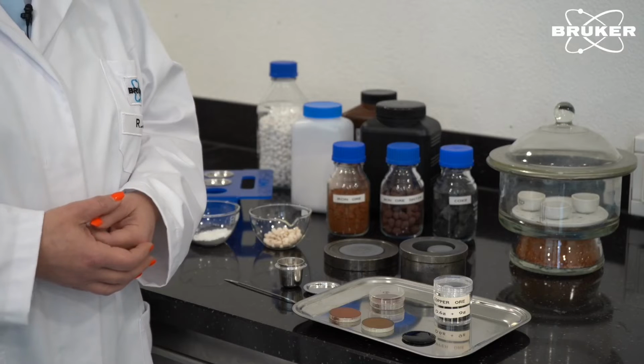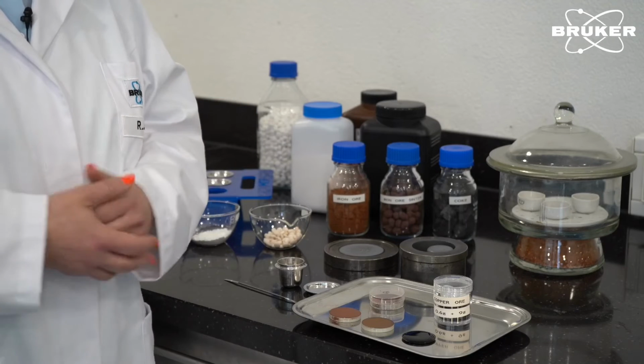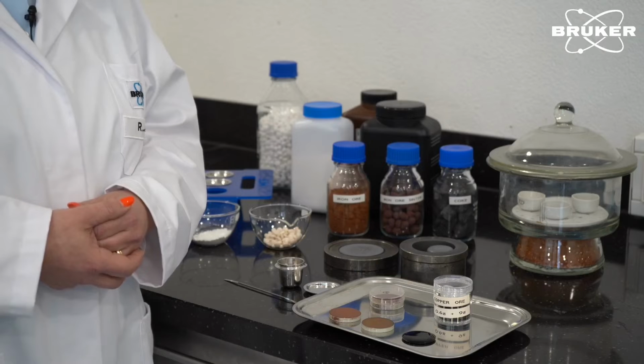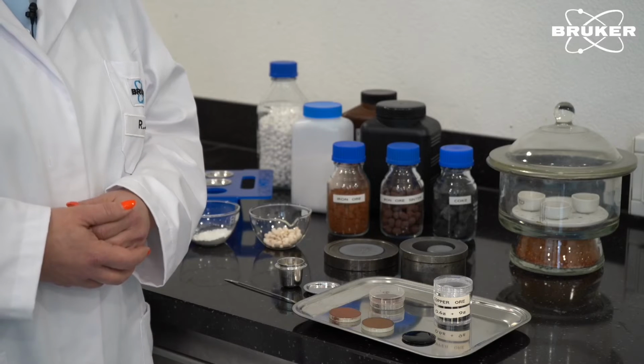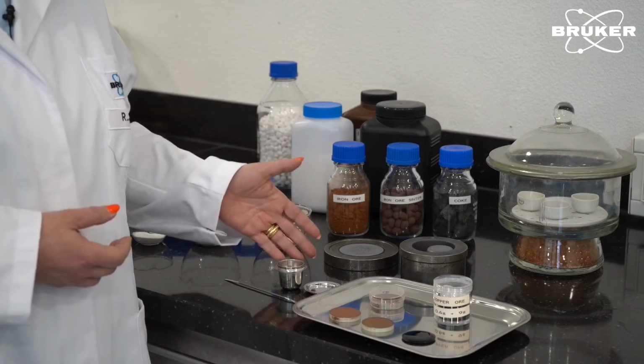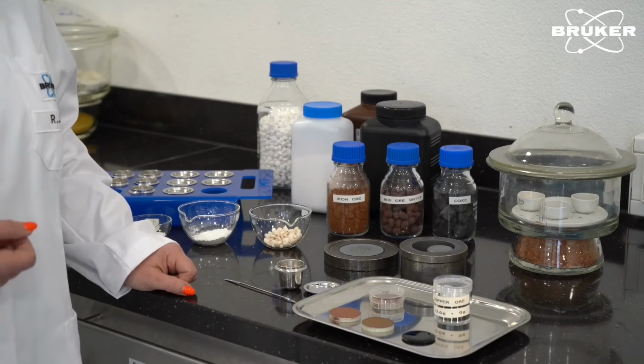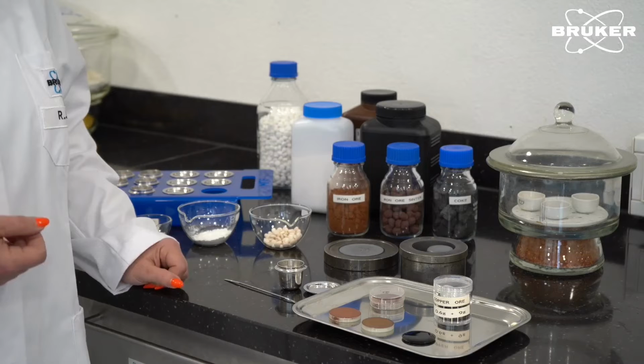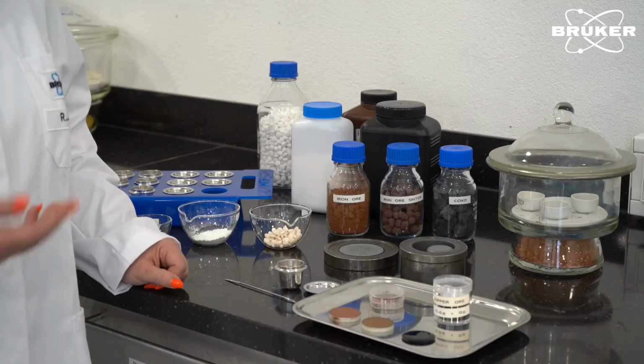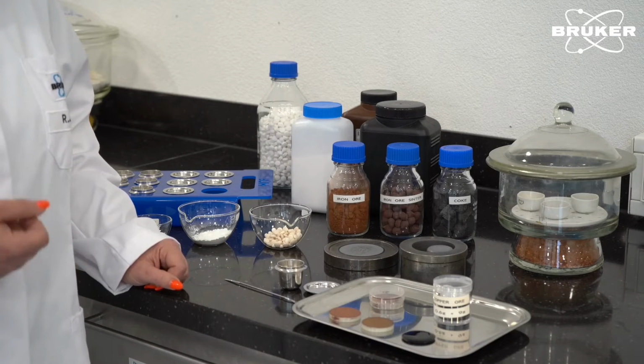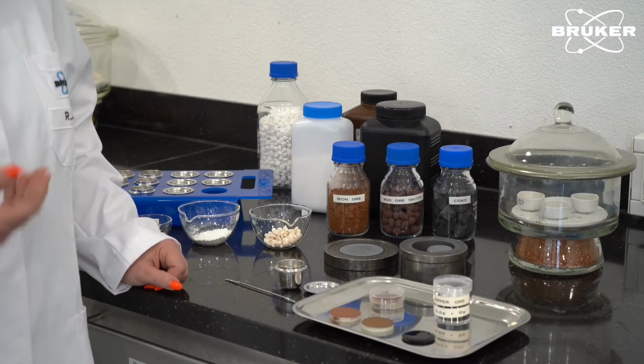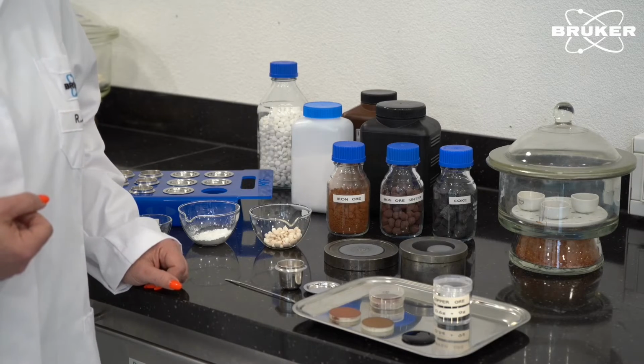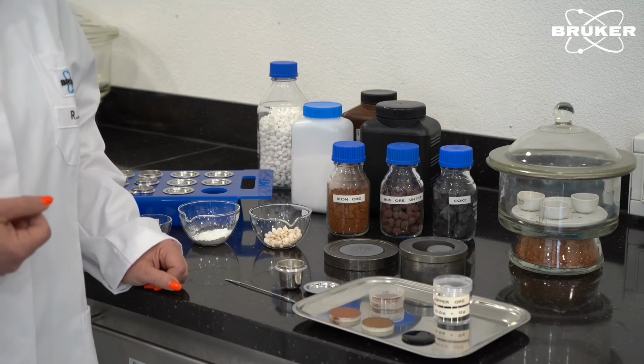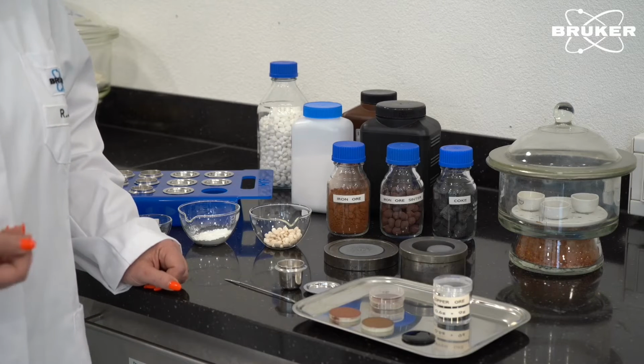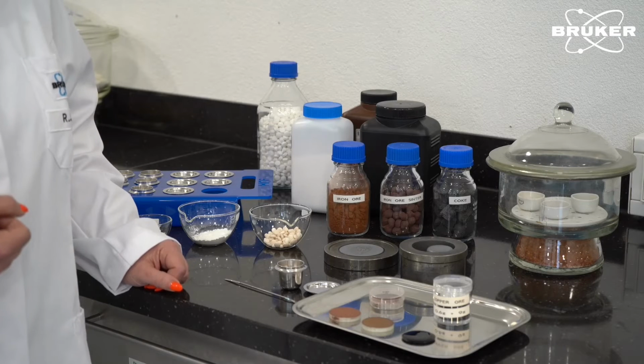In a mining production unit, where there's always some lack of time due to the high number of process samples, typically the sample is not ignited. In this case, you would run some oxidation steps while the fusion process is running. This means you will have different temperature steps or temperature ramps where the sample is heated up. The temperature which is used also depends a little bit on the material. And you will have some additives. I think in most cases you would use sodium nitrate, which is used to oxidize the sample. Sodium nitrate can be used very easily. It's not hygroscopic and sodium is not part of the iron ore norm, so it can be easily used to prepare the fused bead.